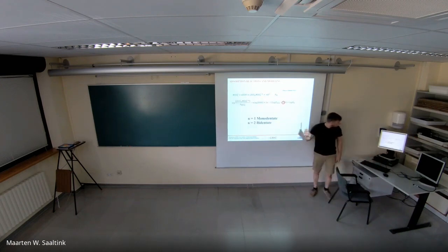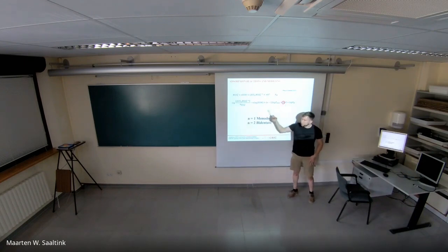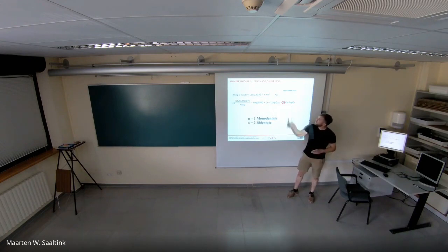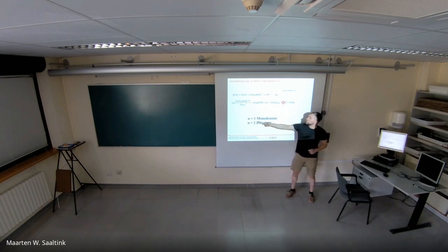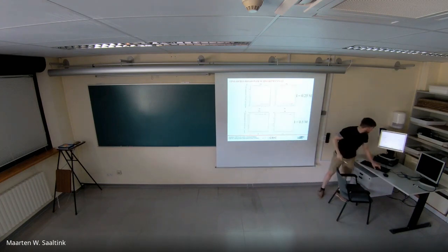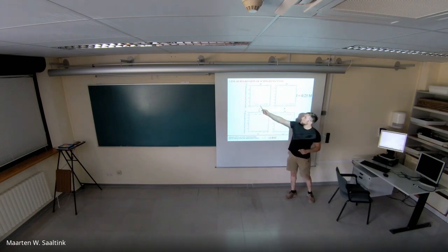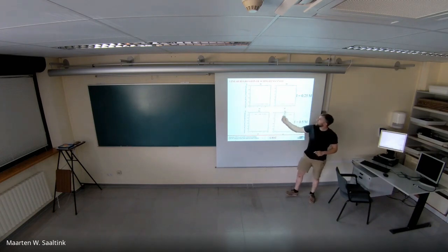Well, this n, if we plot our data and make a linear regression, the slope might be 1 or 2. If it's 1, the reaction will be monodentate and we will use only one site. If it's 2, it will be bidentate. Well, in reality, it can be in the middle, which, for example, in the linear regression of schwertmannite, solution 1 and solution 2, we see that the values are between 1.3 and 1.5. So this is between 1 and 2.